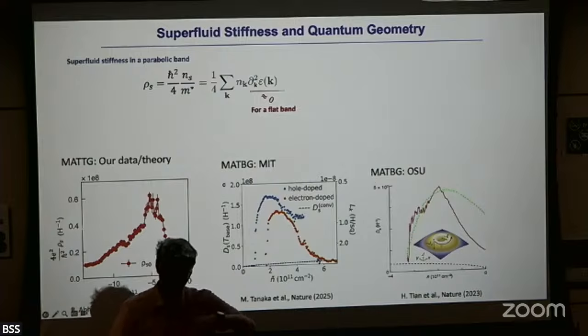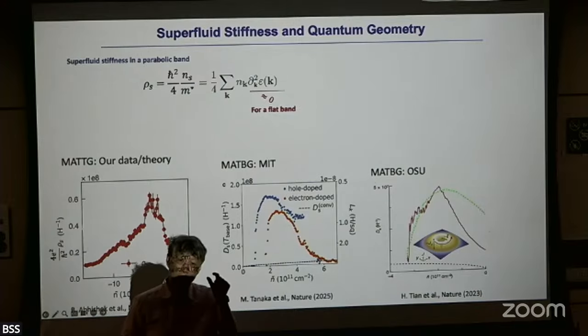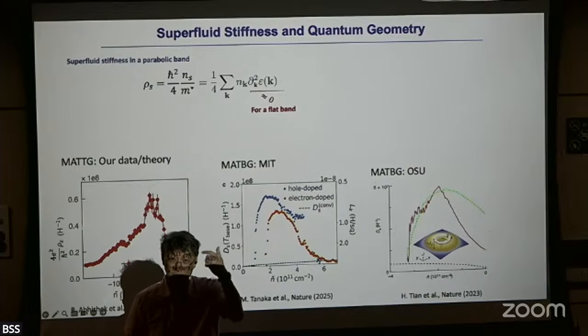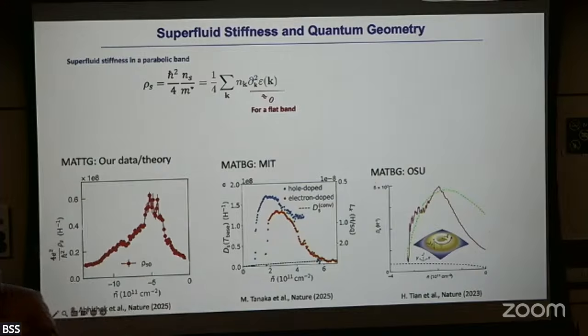Just looking at the temperature dependence of the Shubnikov-de Haas oscillation will give you the cyclotron energy. Cyclotron energy contains mass, and that's one way you can estimate it. Of course, that's under a magnetic field, and there are many things you have to do, but that's the usual way. There are other types of estimation, which more or less agree, right? Now, yeah.